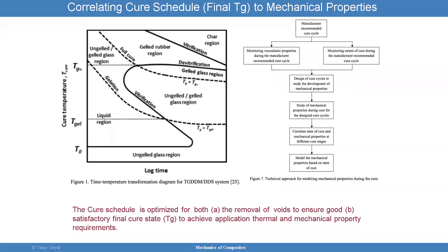And you can design the cure cycles in such a manner that you're considering the cure profile, the temperature profile, the pressure profile, to ensure that you're achieving the mechanical properties that you wanted. And you can study the mechanical properties during cure for various cure cycles. So you could say, okay, the supplier provided me this cure cycle. Let me check a very different cure cycle to see what will happen. You can do delta changes to understand the influence of the cure cycle.